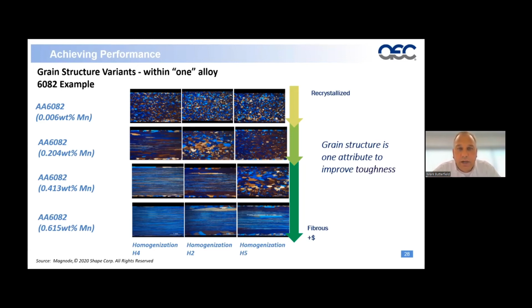Now, each one of those is going to have different characteristics relative to its performance. For example, looking at the bottom left corner, we're seeing a fully fibrous grain, which is going to have high fracture resistance and good intergranular corrosion resistance, versus a recrystallized grain at the top. Doesn't mean one or the other meets your needs, but understanding which one is most critical matters, because the difference in cost is significant. The top right, recrystallized grain, versus the fully fibrous grain requires a different chemistry and a different homogenization, and it extrudes considerably differently.